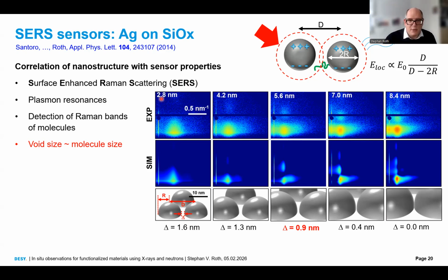This is shown here on top: 2.8 nanometer, 4.2, until 8.4 nanometer deposited thickness of silver. You see the side maximum moving in, meaning that the clusters grow. You see a maximum coming from the top and moving in, meaning that the clusters also grow in height. In the bottom, you see the simulations, and you see by the arrows that we can quite well reproduce the Yoneda peak, the side peak also in its extension, and we can reproduce the height maxima too. This is just this hemispherical model.